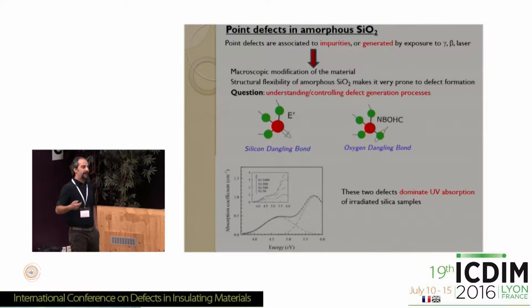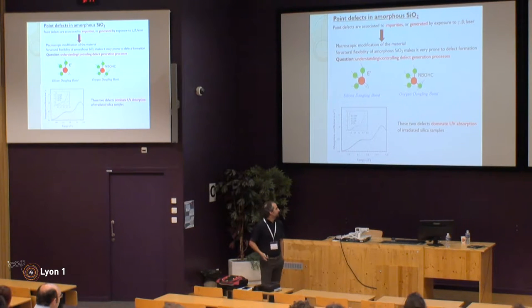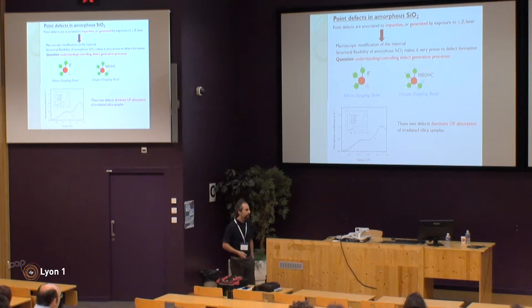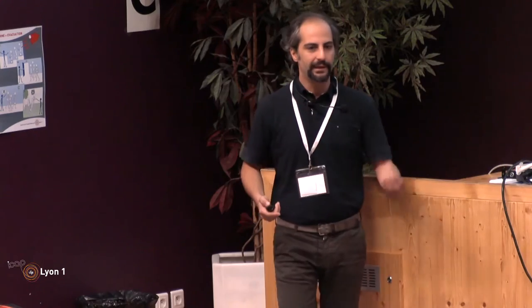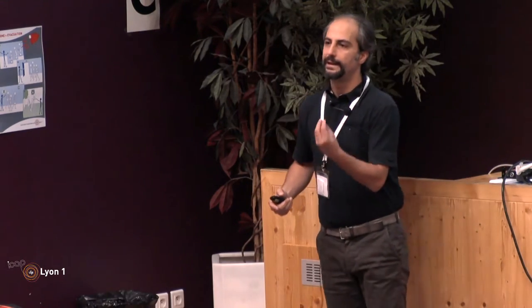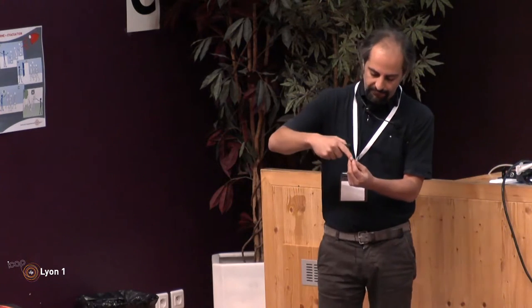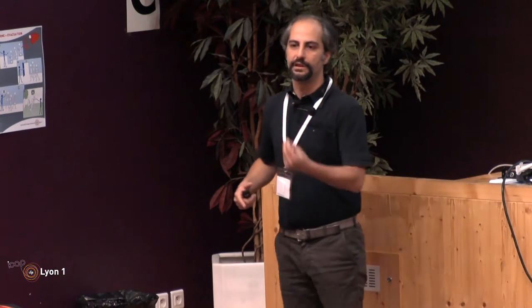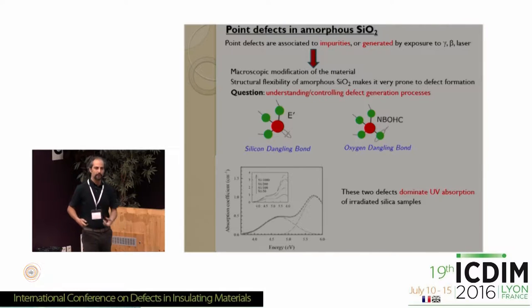And the most common defects that can be found in SiO2, in amorphous SiO2, are these two guys here. These are called the silicon dangling bond and the oxygen dangling bond. So the silicon dangling bond is a defect in which a silicon atom, instead of forming four bonds with oxygen atoms, forms only three, so you are left with one dangling bond. If the same thing occurs on oxygen, you have an oxygen dangling bond. Now, for historical reasons, these are usually called the E prime center and the non-bridging oxygen hole center. But anyway, they are just the silicon and oxygen dangling bonds.